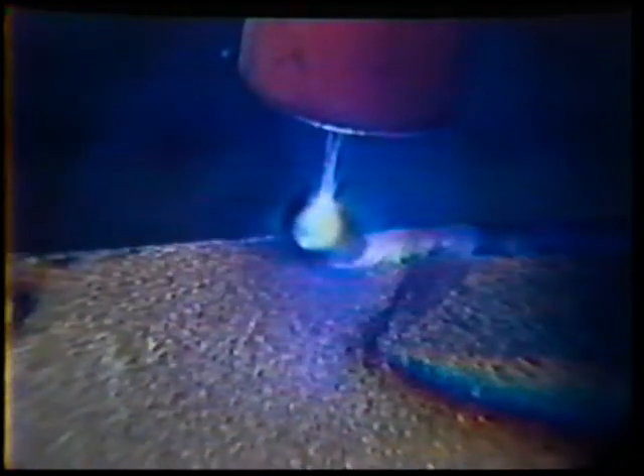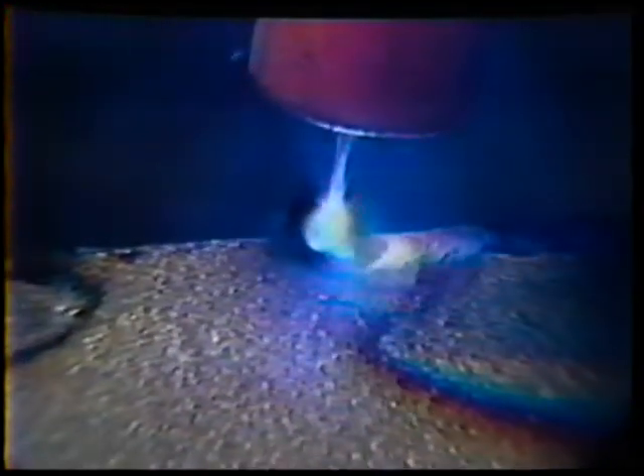Start the arc by pressing the foot pedal and move the torch evenly along the joint as the edges melt to form the bead. Be sure to keep the electrode tip centered in the joint. At the end of the joint, release the foot pedal and continue holding the torch over the solidifying puddle to prevent oxidation.